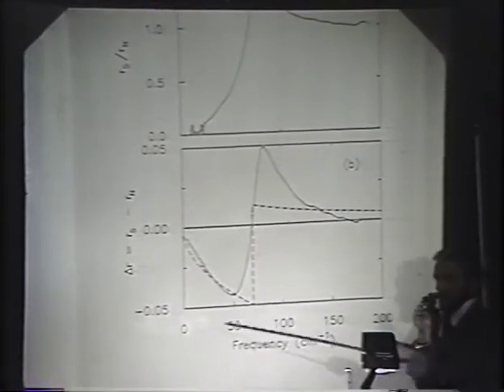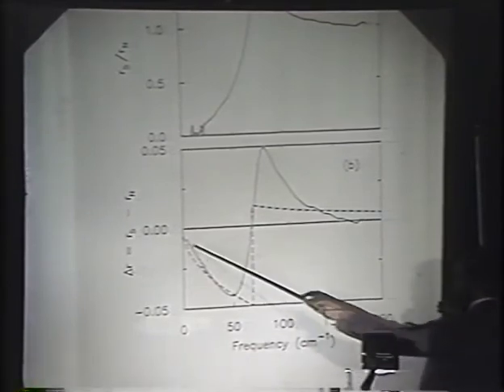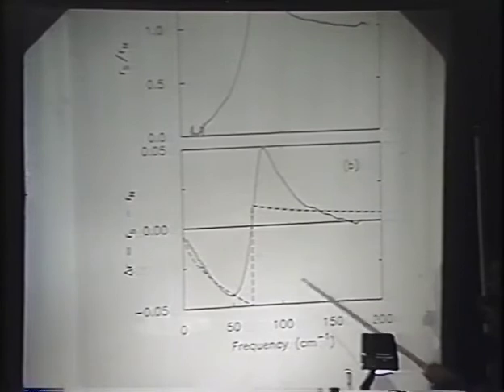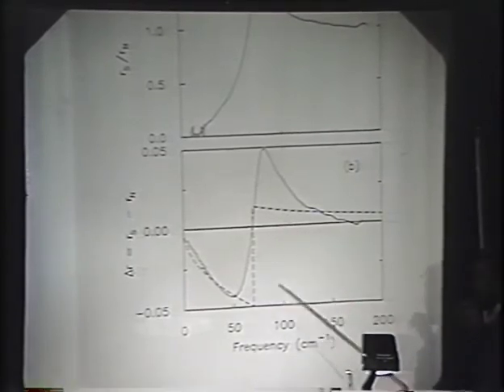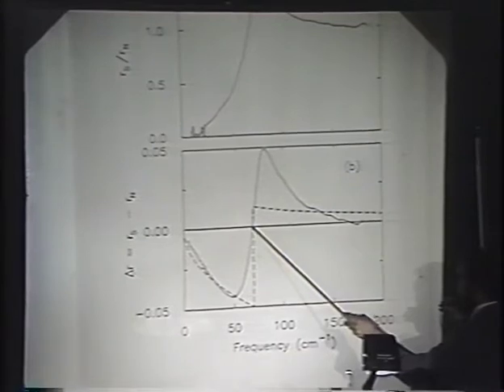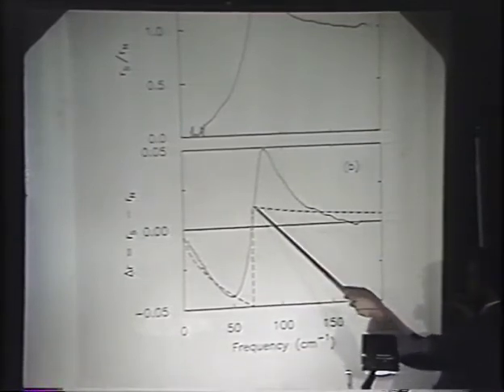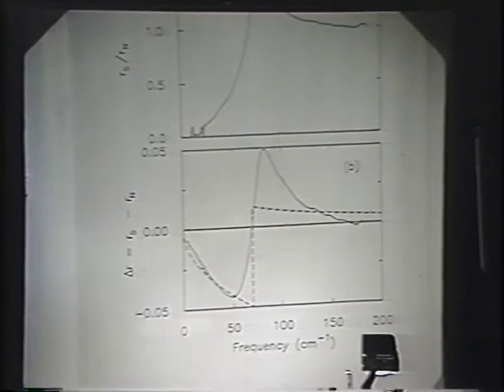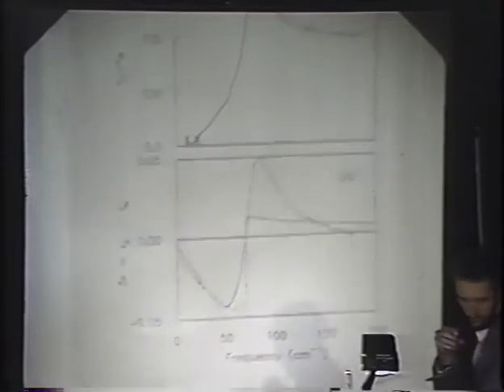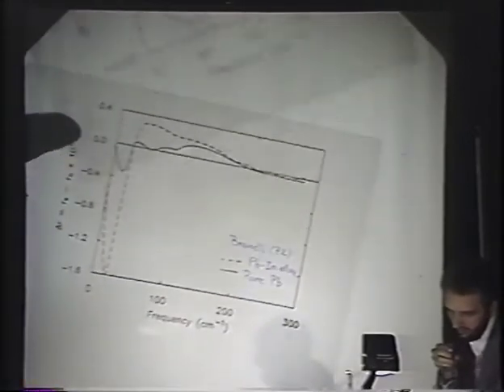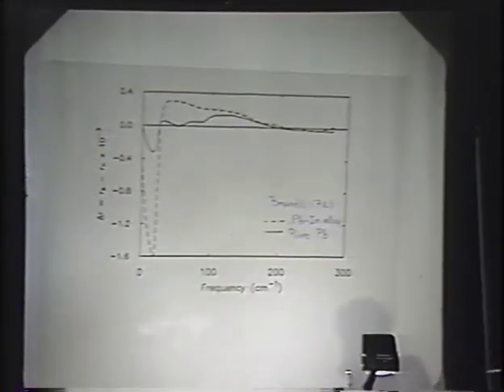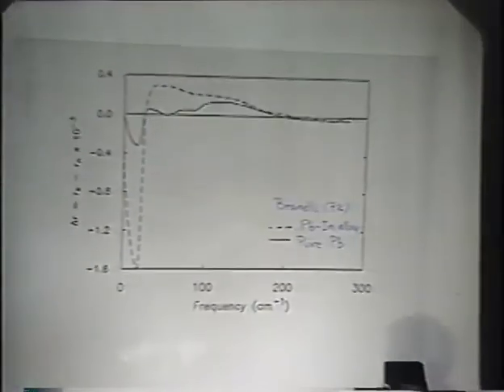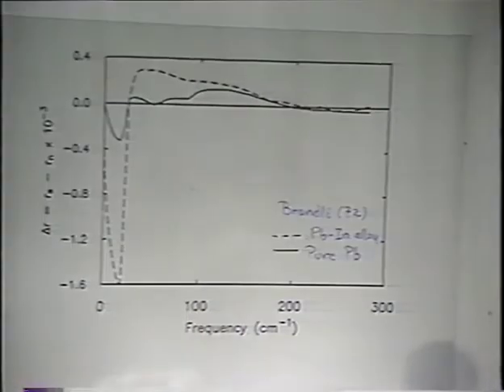Now, if you take that elastic scattering model that I wrote down from Allen, you get this dashed curve as a fit. And you can see that there really is something interesting going on here, that there's this huge peak, and it's much greater than anything that you would see from just the elastic case. And it's much more compressed in frequency space than in the prediction. I can take that and compare it to, say, lead. And you'll see that the dashed curve is for an alloy of lead, and it really looks quite like the elastic prediction. So something interesting is going on here.